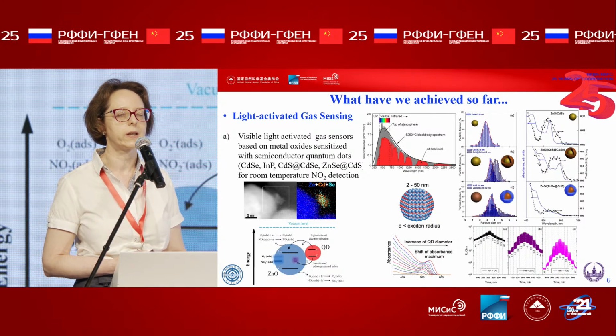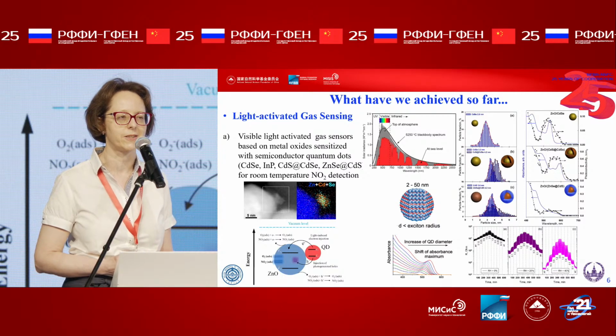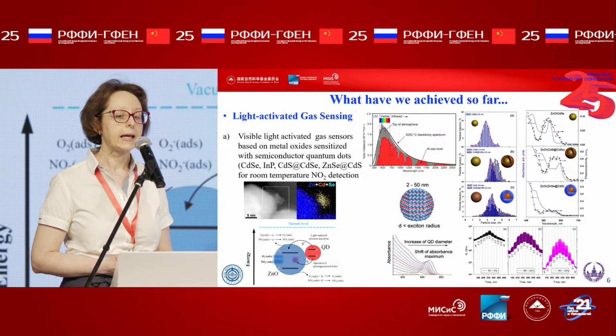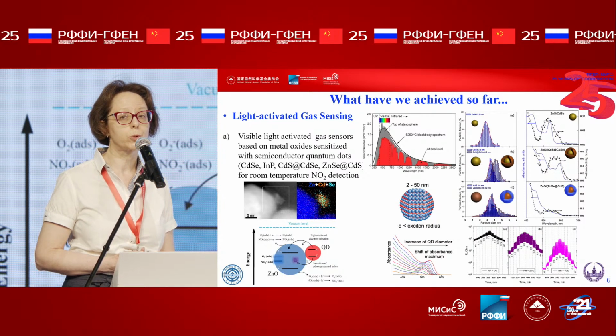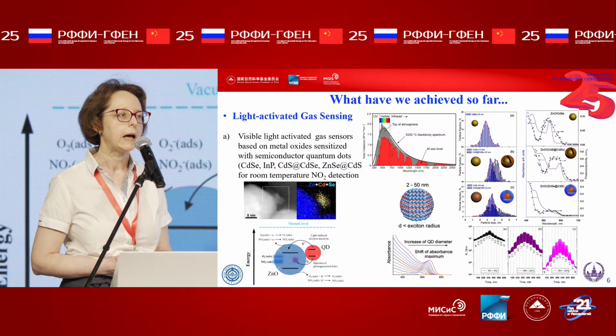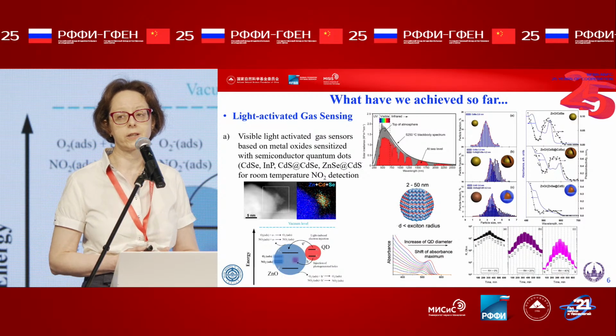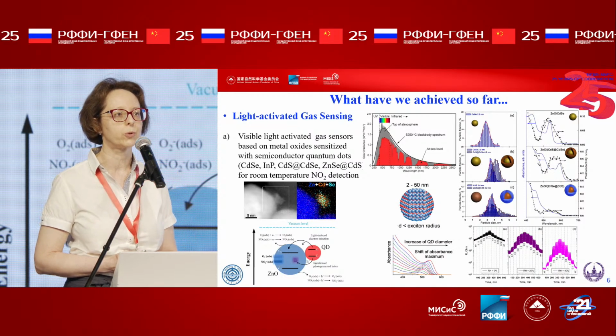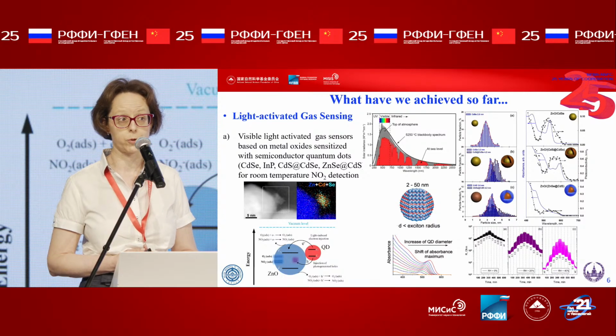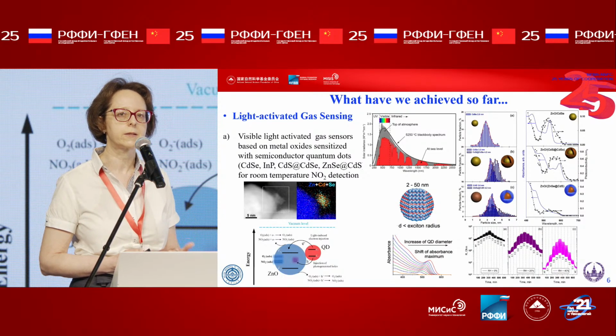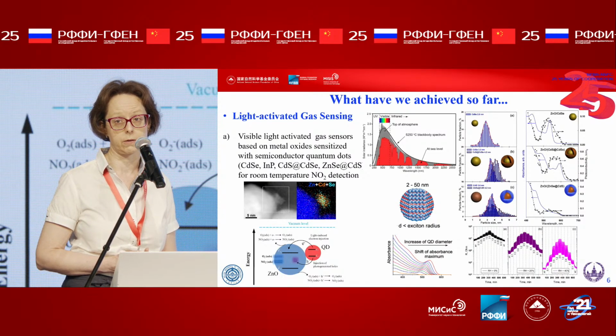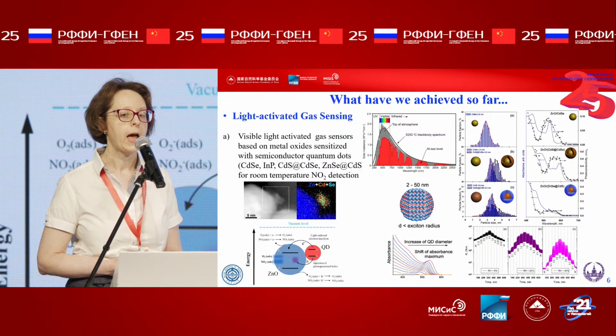And we usually use the green light, which has the maximum intensity. And it is very important that such sensors can work not only in laboratory conditions in dry air, but also in real conditions in humid atmosphere. And this fact is really very important for practice.